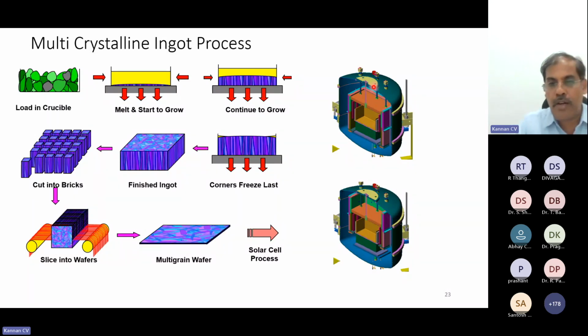So this is the overall furnace design, where the crucible, this is the inner side of the crucible, where the crucible will be lying here and polysilicon will be loaded here. Then initially this will be closed, and there is a heater here. The heater will heat the complete polysilicon material. Once it reaches a certain temperature, then there is a cooling chamber. This is the chamber where cooling water, 18 degree chilled water, is flowing with high flow, high pressure. It is flowing on the chamber, and during the melting process, the chamber is completely isolated through this heat